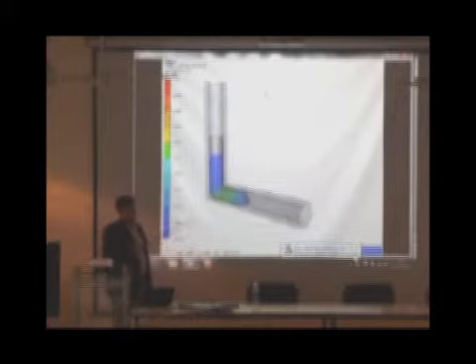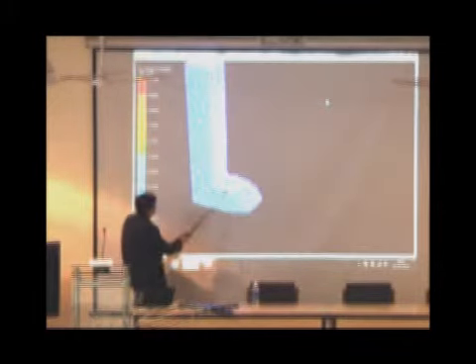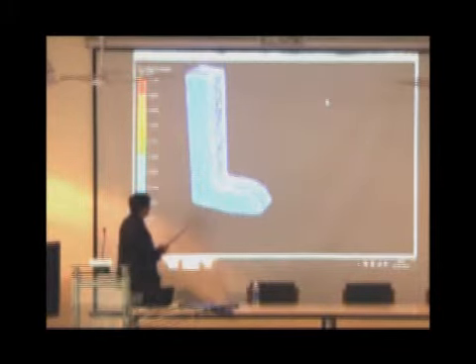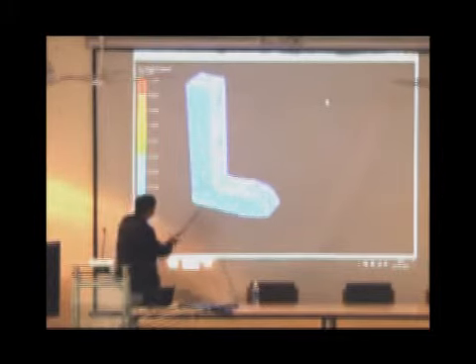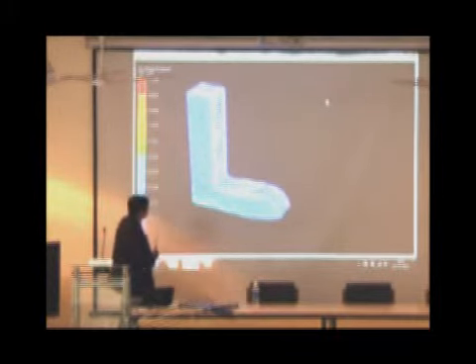This is the region where sudden deformation takes place immediately. It takes a turn over here and sudden deformation is taking place. This is equivalent plastic strain field that is being shown. Average we are getting around 1.4. But to get uniform strain, we need different number of passes.